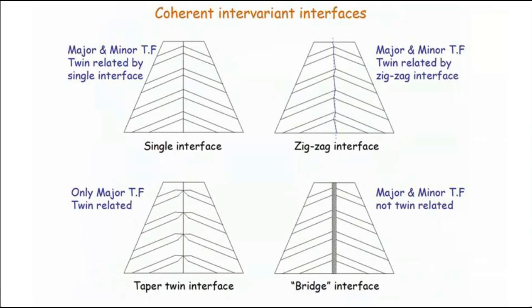But in case the minor twin fraction is not twin related, now that is a disturbing element. Why should you ever get this situation? So let's take a case where the minor fellow is not twin related. Then it still can form a twin interface if we pinch it away. Essentially, by pinching it away, what it means is that at the interface there is no minor twin fraction. It is only the major that exists at this very point. So at that point, you will have only the major twin related, and it's so easy to twin relate, because we have started out saying that it is twin related.